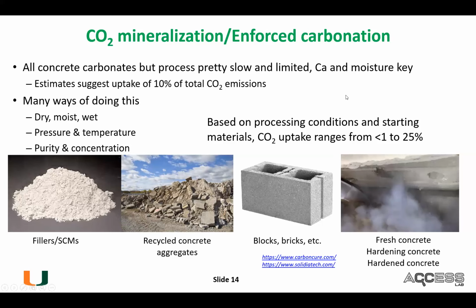There have been many papers that discuss what this uptake comes out to. The ones that I've seen generally agree that about 10% of the total CO2 emissions you make from concrete can be regained over 30 to 50 years simply by doing nothing. You just have the concrete, and it's slowly absorbing the carbon. It's not absorbing a great amount, but because there's maybe 300 billion tons of concrete out there, it's going to keep on taking in carbon.